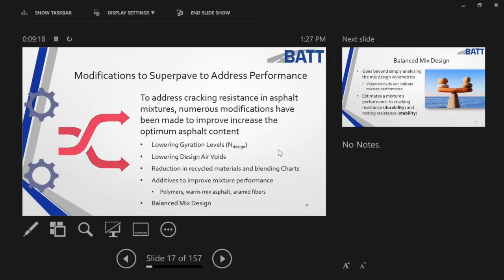So now we're backing that off. We're looking at lowering design air voids. Kentucky alone is moving from about a 4.0 to about a 3.5 in air voids, in addition to lowering gyration levels. And again, that's playing with volumetrics in order to get the end result they want on the performance side. Reduction in recycled materials, encouraging more of the blending charts to understand what the final product is. Additives are another change: the polymers, the warm mix, and the aramid fibers we're going to hear about today.